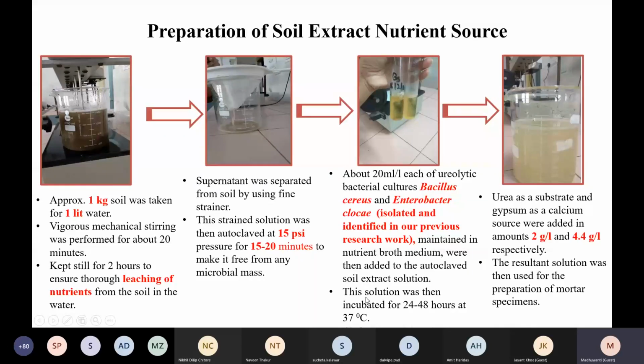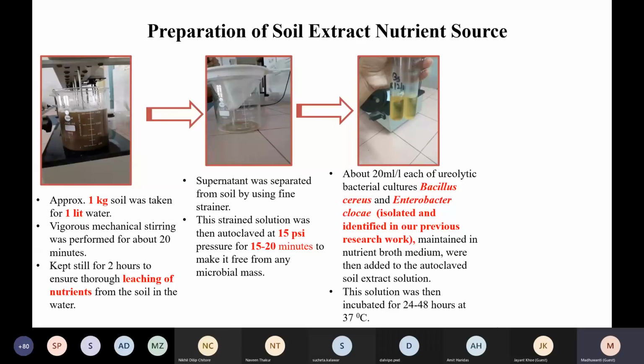Now, what we did is that this solution, meaning the supernatant along with these two cultures of bacteria, was then incubated for 24 to 48 hours at 37 degrees Celsius. Why is this done? This incubation is done to provide the optimum temperature for the bacteria, and the optimum temperature for ureolytic bacteria is 37 degrees Celsius. That we have shown in our laboratory by doing a number of trial and error experiments. It is a standard procedure in microbiology labs to keep the cultures in an incubator at the optimum temperature so that we get optimum growth in a short period of 24 to 48 hours.